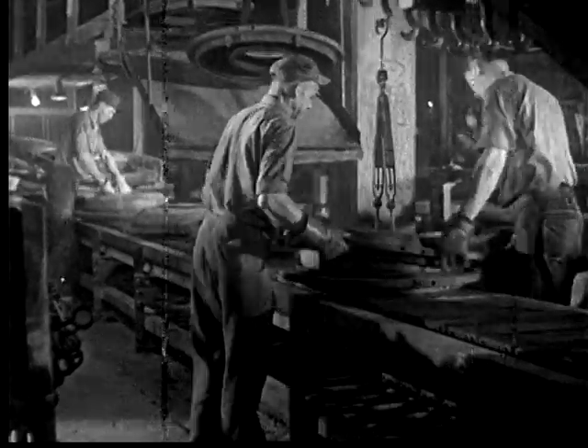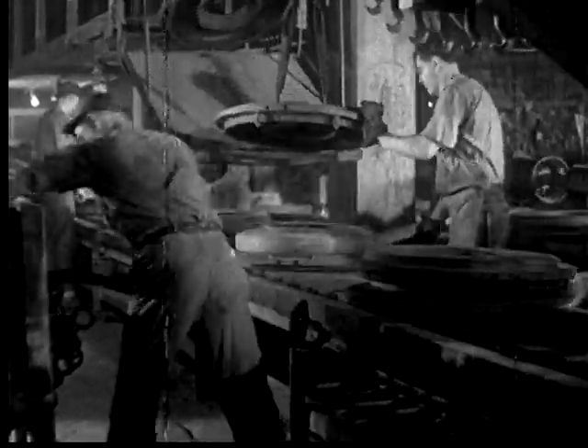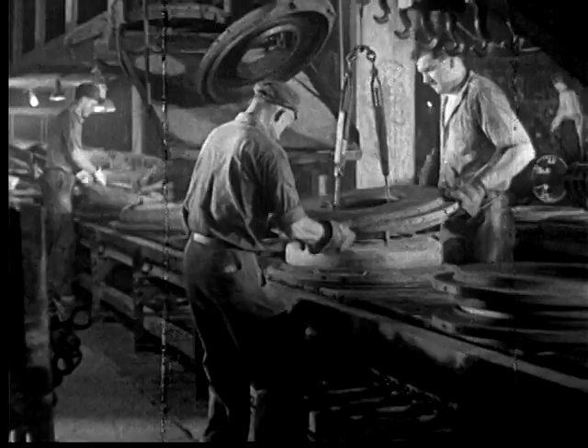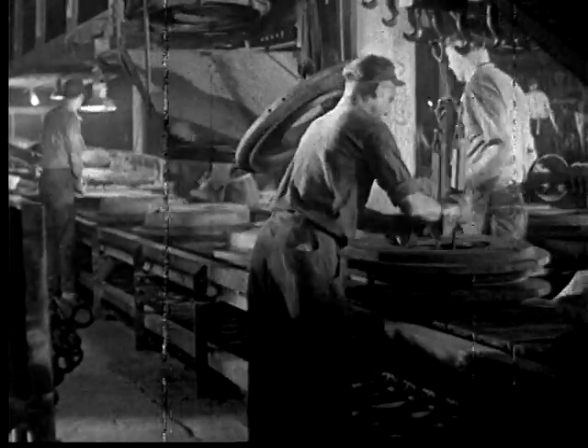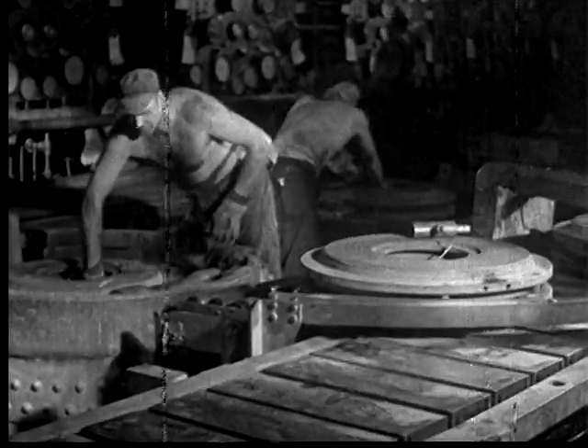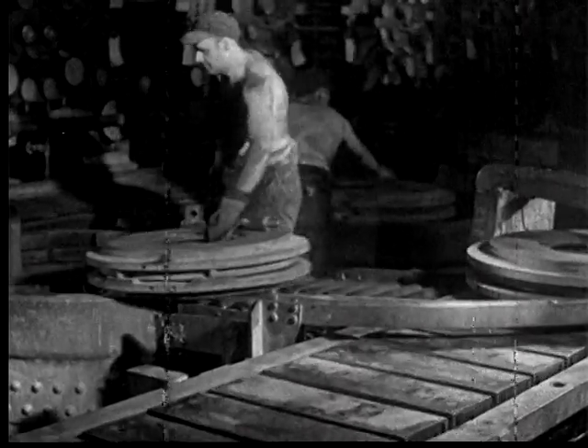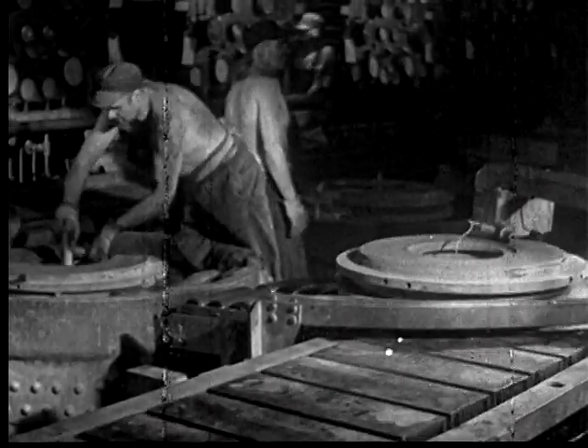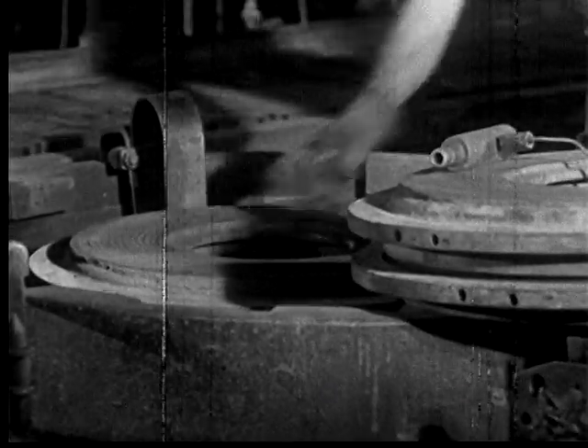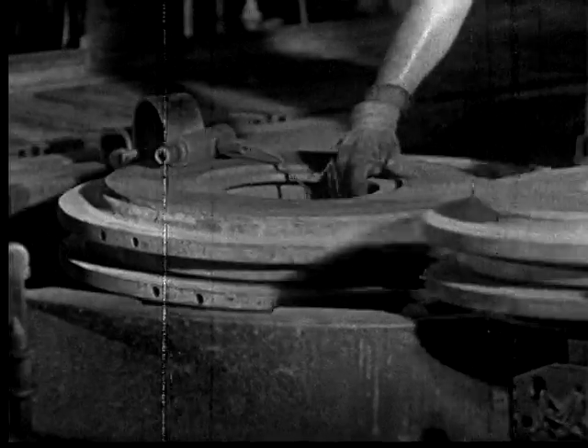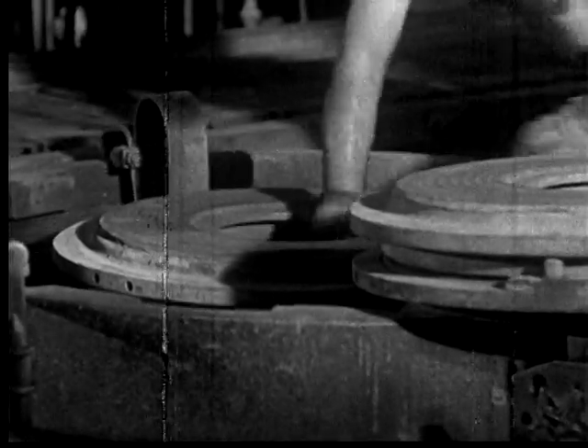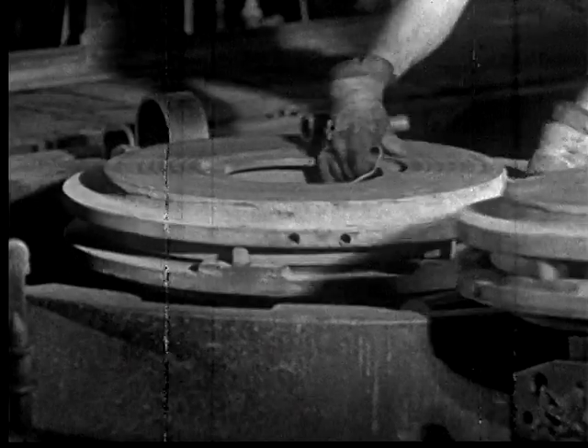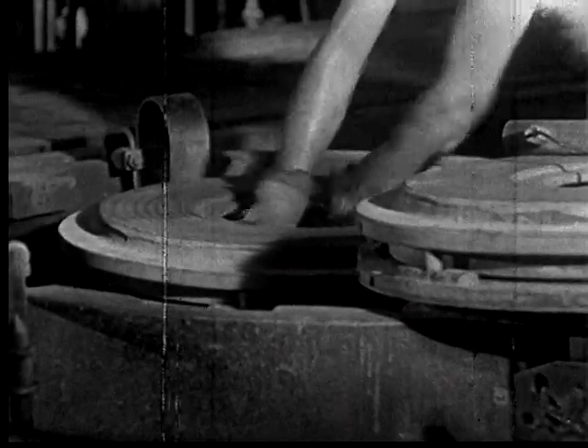Because after the tire is placed into the mold and the top half of the mold clamped down, it's lowered into a huge boiler or vulcanizer, and a fitting is attached to the water bag inside the tire. 28 molds are placed in each vulcanizer, each mold fitted with a water connection. A hydraulic ram gradually lowers the molds as they're placed. The water fittings interlock, forming a pipeline.